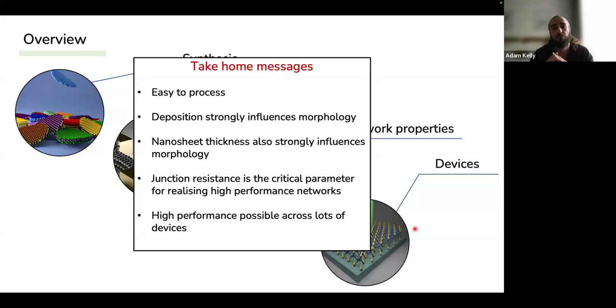Yes, it is. So the band gap of some materials is thickness dependent. And what you do is, after you apply the liquid phase exfoliation process, you will have a dispersion with materials with lots of different thicknesses in there. And what you do then is the cascade centrifugation technique, where you do iterative centrifugation steps, and then the sediment in there will have nanosheets of different thicknesses. Now, depending on how closely together you put the centrifugation trapping speeds, this will change the distribution of your thicknesses. So if you want a very, very specific tight band gap, nanosheets that are very, very close together in band gap, you will have to do very, very close centrifugation speeds.